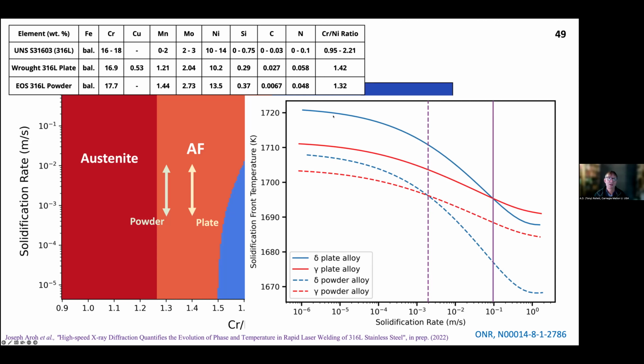Moreover, the dependence on rate is much stronger for the ferritic phase than for the FCC phase, the gamma phase. And so what that results is you expect ferrite at low cooling rates, but the FCC is going to win at high rates. And that crossover point is very sensitive to the exact composition. And so we were able to establish that some plate material had a different crossover point than a powder that is standard powder supplied for 3D printing. I can't say that we understand why these powders might be different from regular plate, and be shifted a bit towards the austenite stability, but it's certainly the result. And there are many microstructural consequences of that, but I don't have time to go into that.